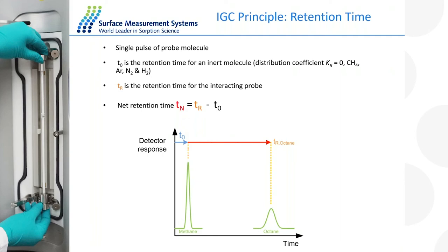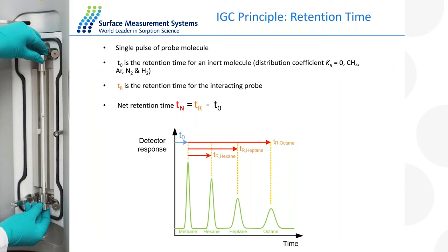If I know the flow rate of my carrier gas — typically about 10 cc/min — then from TN multiplied by the flow rate I get VN, the retention volume. If I put different smaller molecules through, they will absorb for a shorter period of time since they have lower adhesive forces. But in today's experiments, we're typically going to use just one molecule such as octane or hexane, and look at the retention behaviour as a function of temperature — because Tg is what we're interested in.